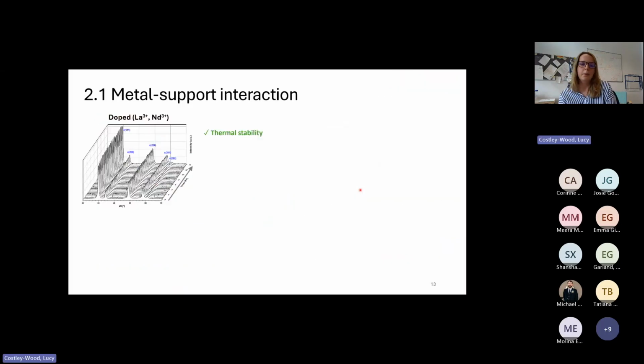So to summarize this part on metal support interaction: yes, these materials are doped because it increases the thermal stability. That means we improve the lifetime of the catalyst, and also means we can widen our operational window, because the temperatures which three-way catalysts are exposed to can vary from 100 degrees when you first turn on your car to up to 900 degrees during really harsh acceleration events. So if we need the material to be able to respond quickly to these changing temperatures, and on the rare earth doped material the palladium can reoxidize more and then back, that seems like an advantage.